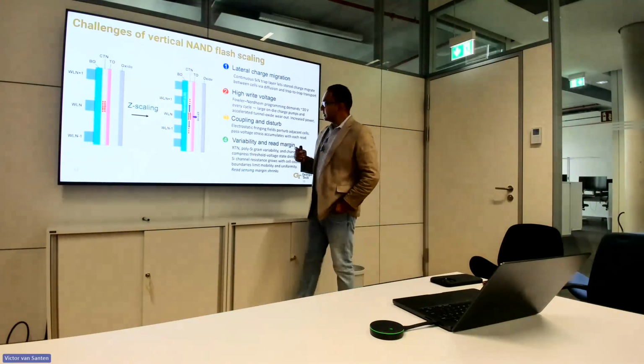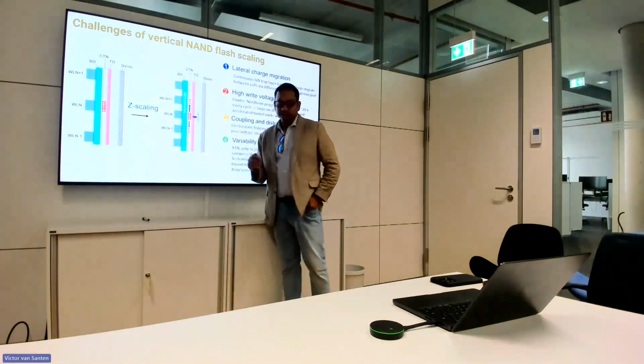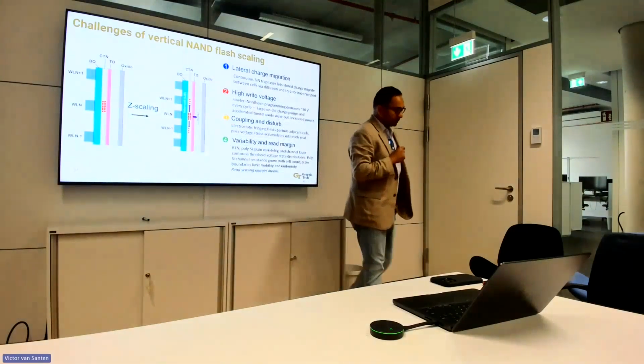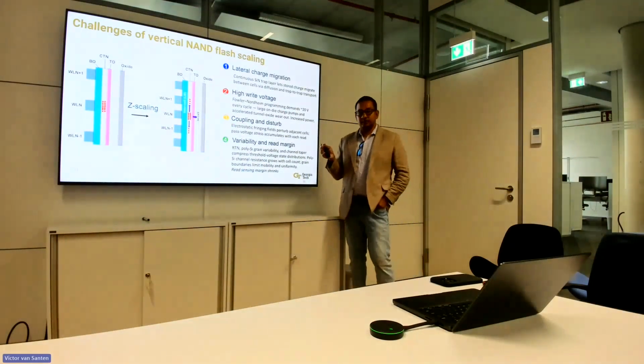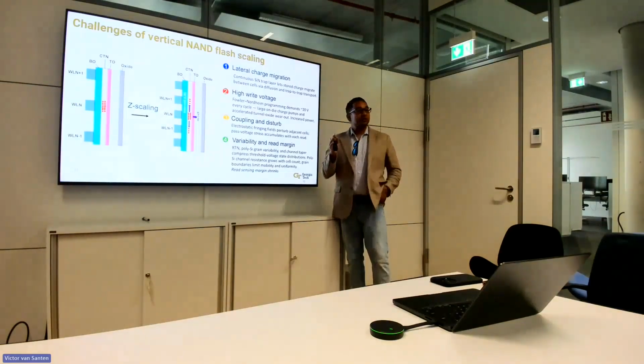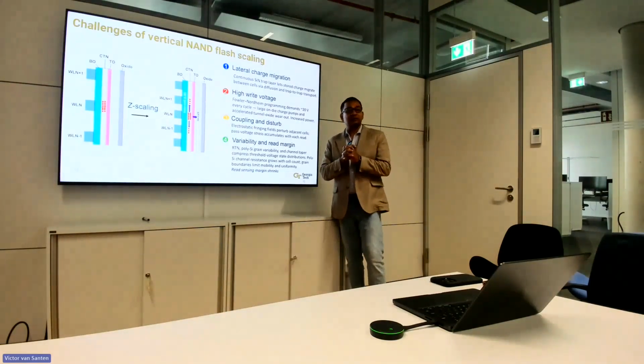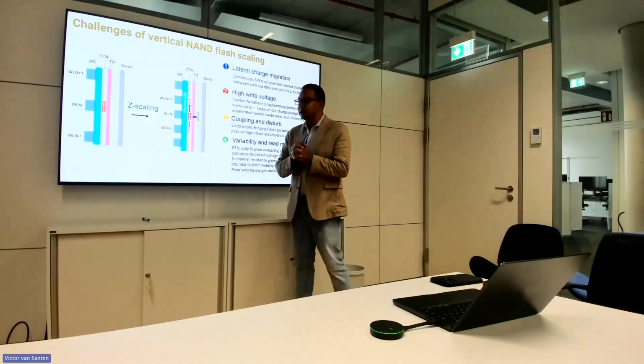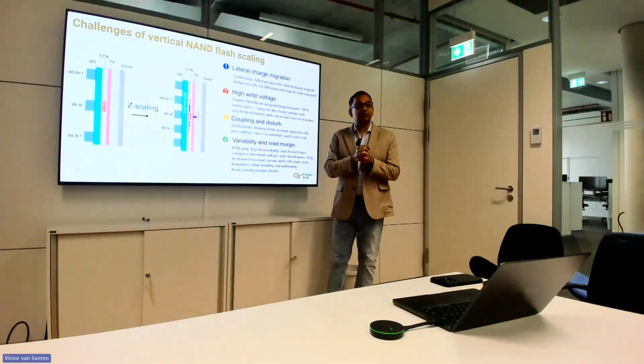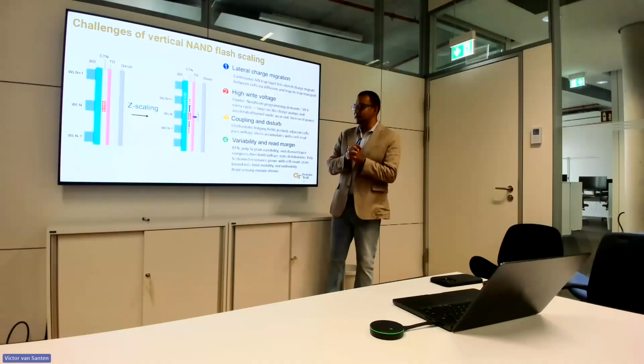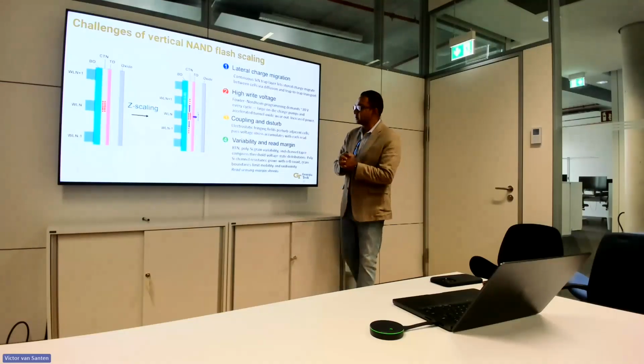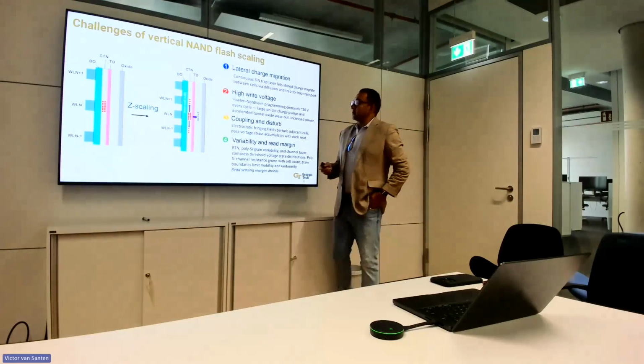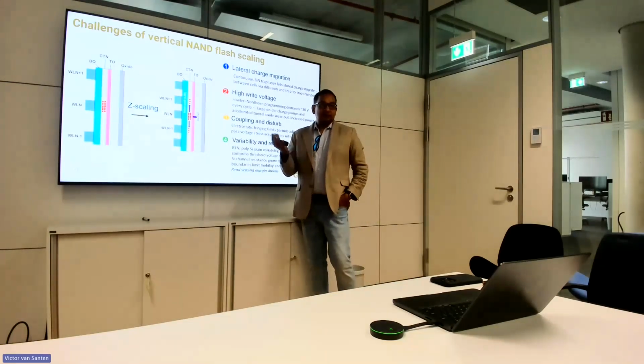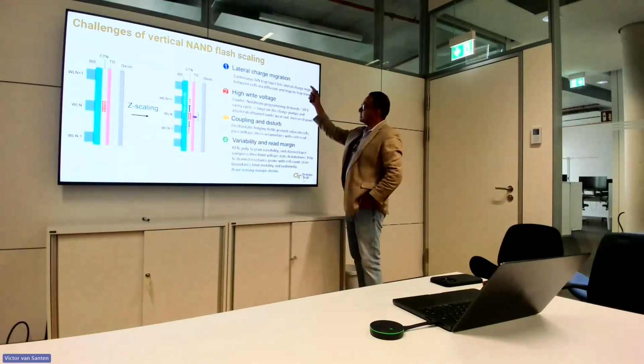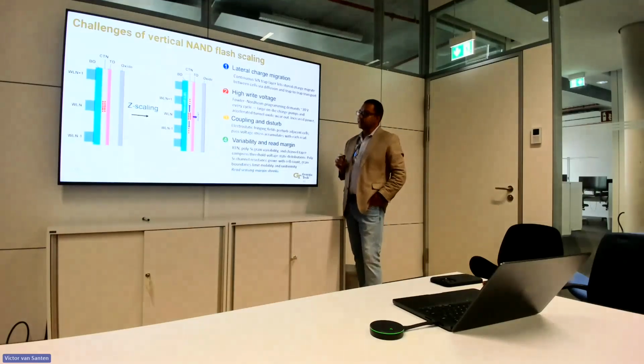And this is a key challenge, because if this happens, then the VT distribution gets widened, and that creates significant challenges when you are actually trying to store terabyte-scale data in it. So in other words, you put some data in it, and after some time you see that it's lost. Okay. So that's the first challenge. And this is really a critical challenge.